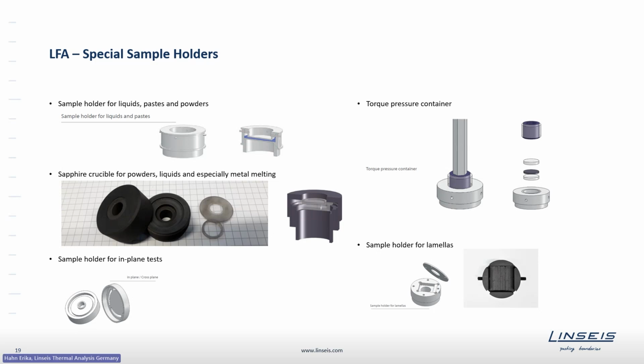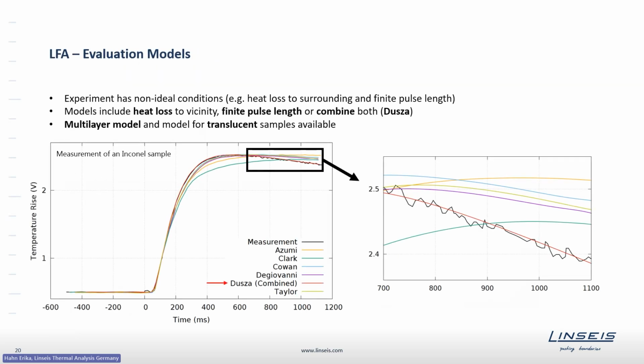As soon as the test is done, one also needs to evaluate the measurements. For that, there are several models available. These models are necessary as the experiment has non-ideal conditions, deviating from the ideal case, so from theory. These non-ideal conditions are heat losses to the surrounding, to the sample holder, for example, and the so-called finite pulse length effects appearing for